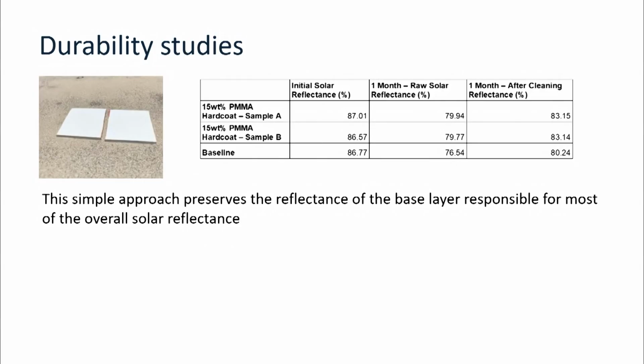We've also done a lot of durability studies outdoors to look at how adding this kind of coating on top actually preserves the durability of the bulk layer, the base paint, which is where the degradation really happens. And so we think this is very exciting and very practical. It solves an immediate problem that is going to make this kind of technology useful.